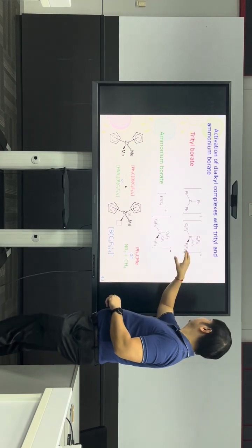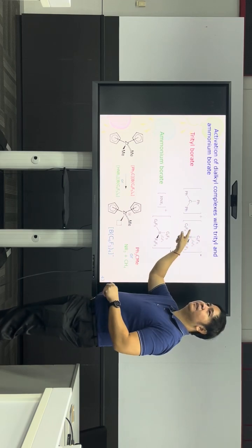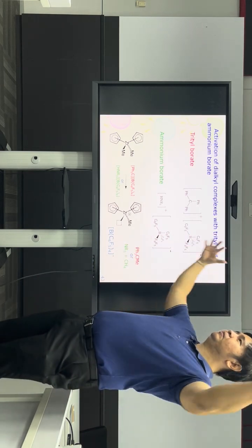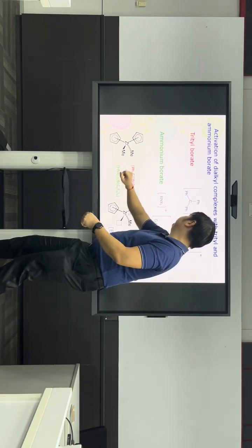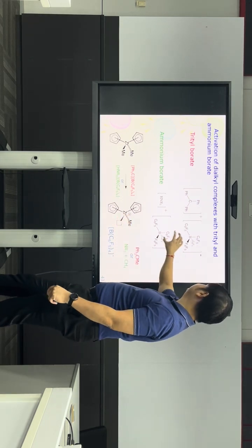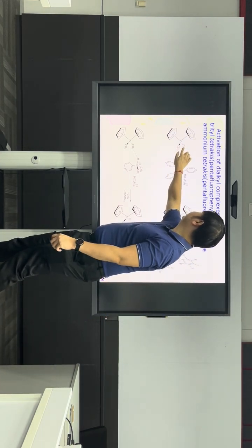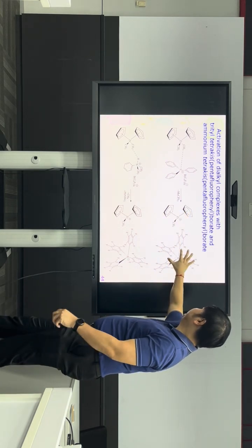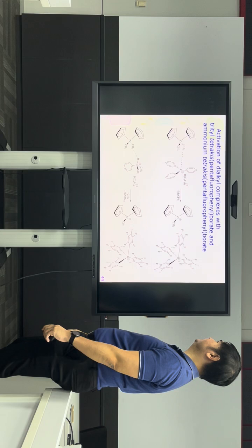It looks something like this. The borate has C6F5 groups, but not three of them, now they have four of them. So this group will be non-coordinating. It cannot coordinate to the metal. It's a big bulky group with a negative charge. The trityl group will react with the metal group and give you a perfectly positive charge. Trityl abstracts the methyl group and gives you a positive zirconium cation, and the anion is the big bulky group. So this gives you more activity for the catalyst.